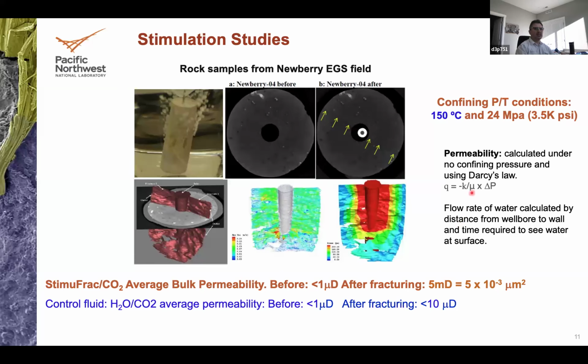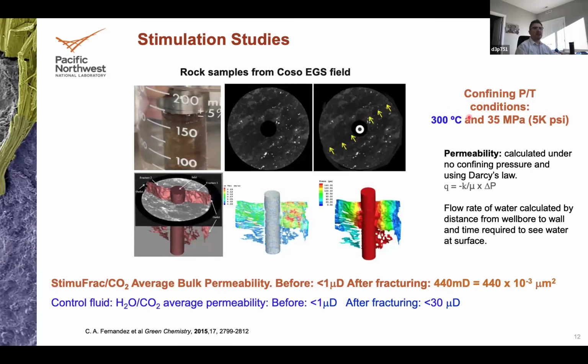And what we've observed was not only that the StimuFrac CO2 was fracturing at lower pressures than conventional fluids like water, CO2, or the combination of water and CO2, but also that the permeability of the sample was significantly higher, orders of magnitude higher, than in the case of the same sample in the absence of the polymer, so water, CO2. And this was not only at lower temperatures of 150 Celsius, but also at temperatures as high as 300 Celsius. We were able to push the limit of the reactor to 300 Celsius and get similar results, where we have very high permeability using StimuFrac CO2 versus the same solution in the absence of the polymer.